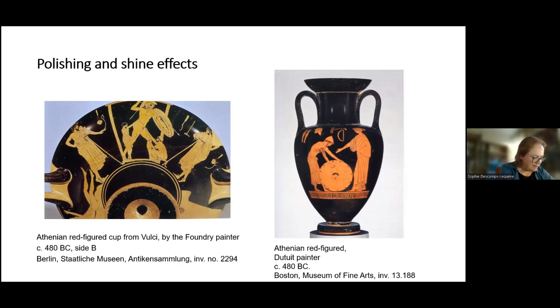From the first stage of scraping the cast skin to the final polishing of surfaces to accentuate their shine, bronze workers used a variety of abrasive materials and tools: emery ground to a powder and mixed with oil, stones of different hardnesses, first coarse and then finer and finer up to pumice stone, and metal scrapers. The effects of light were empirically known to ancient sculptors, who were well aware that bronze still has a matte, golden appearance, not a shiny one, after the action of pumice stone.